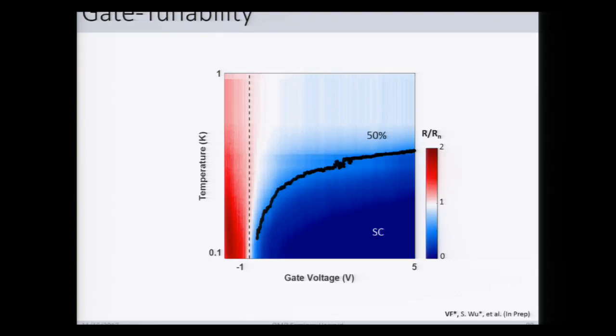This line indicates the critical temperature as defined by the 50% value relative to the normal state. As we deplete, the critical temperature gets lowered, and eventually we get to a point where there doesn't seem to be much temperature dependence at all. And then at yet lower density, we go from white to red, which indicates an insulating temperature dependence, indicative of the topological insulator phase. So it turns out that this superconducting state, this density, is around 5 × 10¹² per centimeter squared. It's one of the lowest density 2D superconductors. It appears to be the lowest density superconductor as measured by induced density that we're aware of.